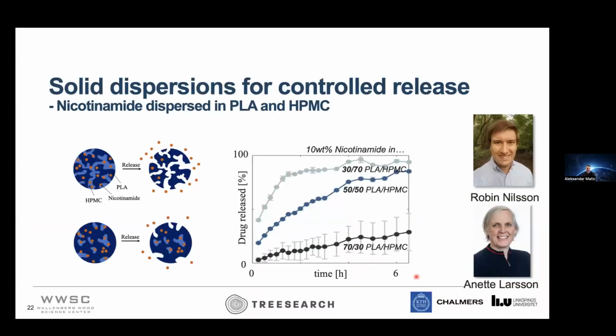So what actual target is here? You have a polymer matrix, a phase-separated polymer matrix with HPMC, hydroxypropyl methyl cellulose, together with polylactic acid polymer, PLA. The HPMC phase is really hydrophilic, which, when you add the dissolution medium, will swell and quite quickly erode away, and then through this process, set the drug free.